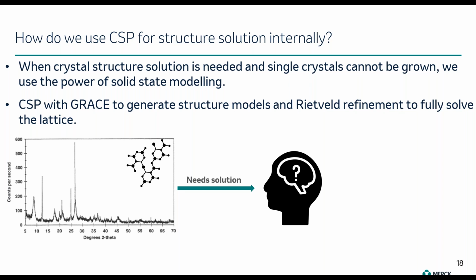So how do we use CSP for structural solution internally in our company? When we need to solve crystal structures and we cannot grow single crystals of sufficient quality, we use the power of solid state modeling. So we perform CSP with Grace to generate structural models, and then we perform Rietveld refinement to fully solve the lattice. So let's say that we have a PXRD pattern and we need a solution.